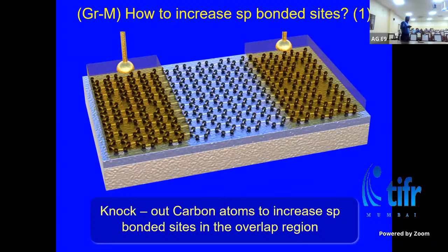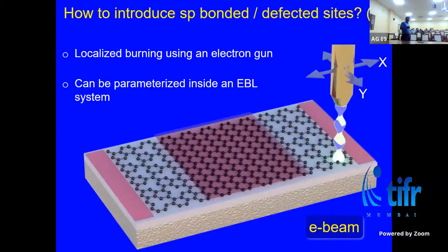So how do we do that? Basically, you have to create these defect sites. One method that we figured out was we can burn regions locally using an electron gun. Now, how do you get the electron gun? You have this available in the e-beam lithography system, right? So you can first develop lithography, you open the contact, and you still have photoresist everywhere else except the contact. And now in the e-beam system, you can program where you want the electron gun to shine high energy electrons, and you can basically burn a local region.